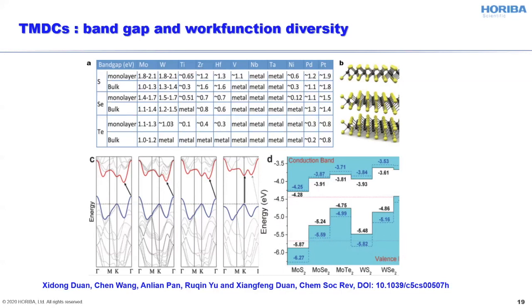As you can see in this band structure diagram, the diversity of the width of the band gap and the work function of the materials is quite extensive. So we can have narrow band gap semiconductors, mostly based on tellurium, high band gap semiconductors based on sulfur, and the position of the Fermi level can vary quite dramatically, which makes it very enticing to combine these materials together, either in the form of vertically stacked materials or growing lateral heterostructures, thus arranging p-n junctions and other interesting electronic formations based on realistically atomically thin materials.